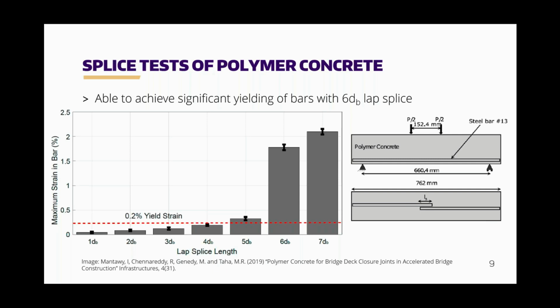And the plot here is showing the maximum bar strain at the peak flexural strength. And you can see that if the bars were lapped for 6 bar diameters or larger, you got significant yielding of the bars. So 6 bar diameters in terms of a lap splice length is comparable with what we would see with UHPC. So that was promising in terms of the results.